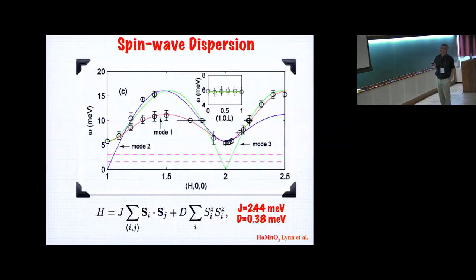This is the traditional stuff, so spin waves. You can, by scanning in different directions, here's in the H00 and here's in an L direction, you can work out dimensionality, so there's no dispersion here and there's lots here. And then by fitting these data, you pick your model that you think is appropriate, and you can get exchange and gap numbers.